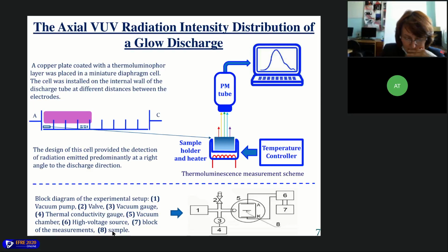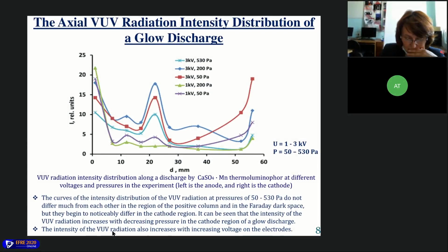Next slide, slide number 8. On this slide you can see the axial vacuum ultraviolet radiation distribution of glow discharge depending on voltage and pressure. The intensity distribution of the detected thermopeaks reflects the vacuum ultraviolet radiation intensity distribution along a discharge. From the figure on the slide, it can be concluded that the glow discharge in air emits photons in the vacuum ultraviolet region practically throughout the length with different intensities. The most intense regions of vacuum ultraviolet radiation are the near-electrode regions, I mean here and here, of the discharge.